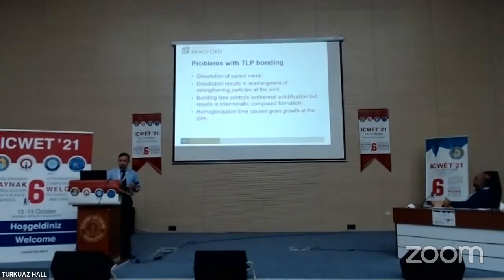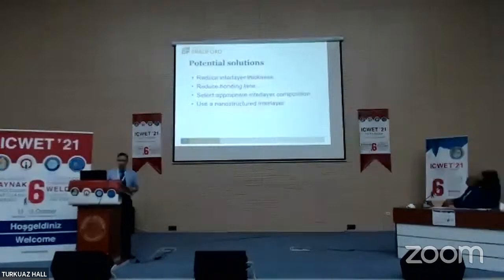So how can we try to change this? How can we try to solve some of this? Well, some, including my team, we've looked at seeing what can happen with the interlayer thickness. Because when we use different interlayer thicknesses, we can control the volume of liquid formed at the joint. Reducing bonding time: if we reduce the bonding time, we can control the volume of intermetallics forming. But if you reduce the bonding time, then we may get a weak joint because the liquid does not flow between the joint interfaces.